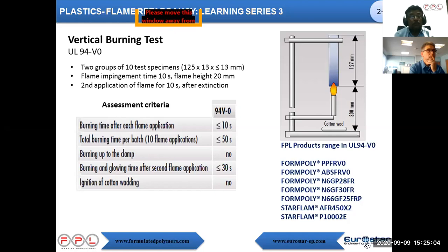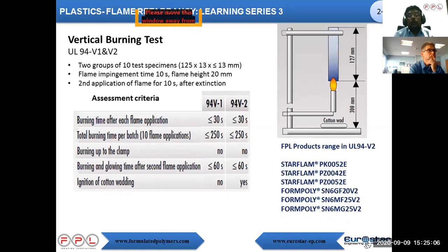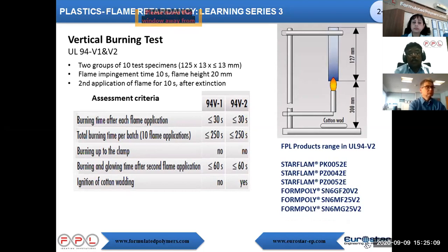Then we move on to the vertical burning UL 94 V1 and V2 test procedure. The test conditions, specimen dimensions and test procedures are the same as in the previous V0 test. Only the acceptance criteria vary in V1 and V2. The total glow time of 10 flames should not exceed 250 seconds, as against 50 seconds in the V0 rating. The burning time of an individual specimen for the first flame should not be more than 30 seconds, and for the second flame it should not be more than 60 seconds.